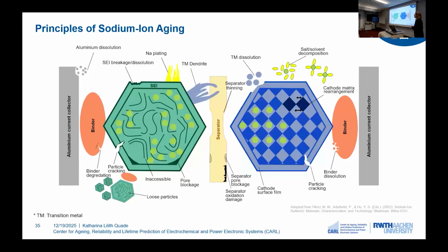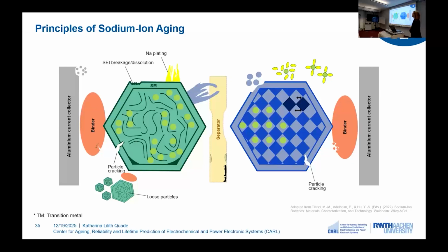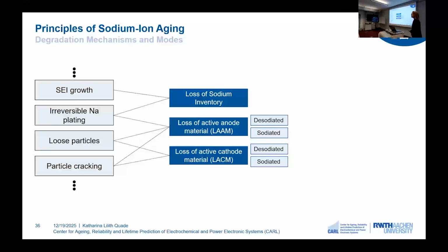And I will now omit aging phenomena that we cannot reliably detect with our non-invasive degradation analysis. And here you can see the reduced amount. Here again, on the left-hand side, however, we can assign these aging phenomena now to so-called degradation modes that you can see here in the middle. And we have three main degradation modes. Loss of sodium inventory, where we lose cyclable sodium. Loss of active anode material, where we lose electrode capacity, and loss of active cathode material, where we again lose electrode capacity.